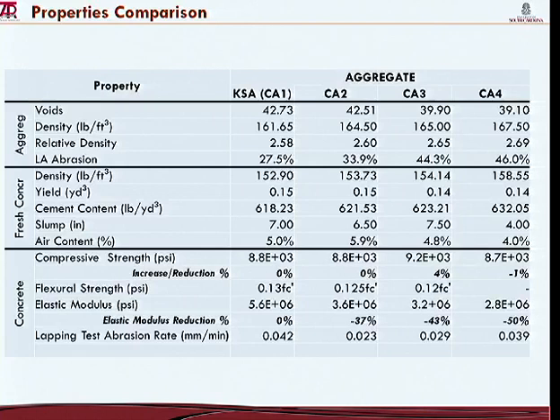For the fresh concrete, same properties for all aggregates. For the hardened concrete, the compressive strength remains the same. Flexural strength about the same, but between 12 and 13% of f'c. And for elastic modulus, we've seen reductions between 37 and 50% just by using a different type of aggregate, the weathered